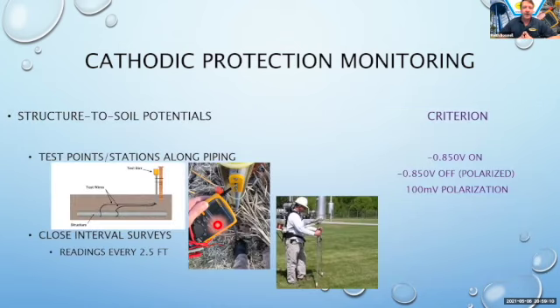The other aspect of monitoring is to obtain a voltage potential of that crude piping to determine how effectively the cathodic protection system is working. This voltage potential gives us a guideline of whether it's meeting a set criterion that identifies the adequacy of cathodic protection. These are performed annually by LESCA, and the test points are random locations along the crude piping system. There's a set of wires connected to the pipe, brought into some above ground feature or test point, in order to make a connection to the pipe and record that voltage potential.